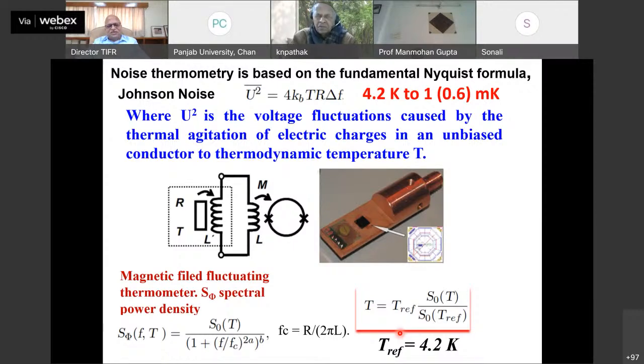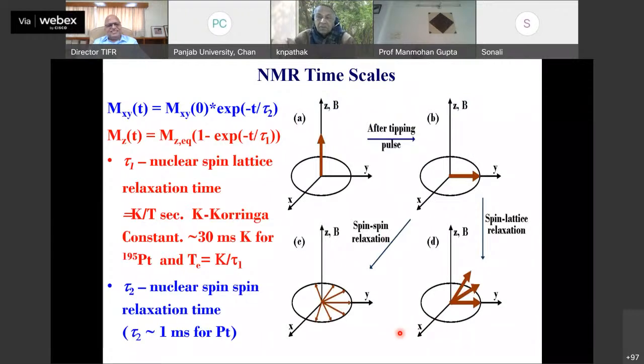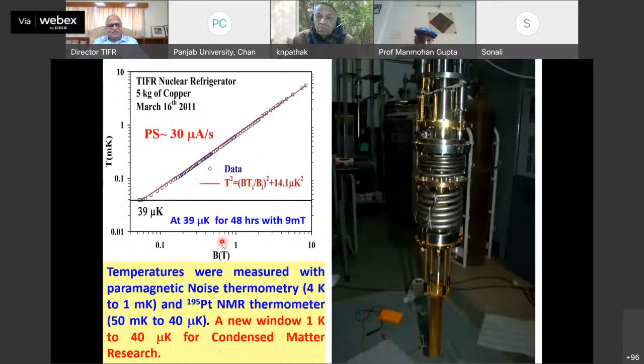Then use this noise sensor to calibrate the NMR thermometer. So what you do, the magnetization goes as M_0 (1 - e^(-t/tau_1)), where tau 2 is the spin relaxation time, and tau 1 is the spin lattice relaxation time. So by measuring the magnetization at different temperatures and taking the ratio, you can also measure the temperature, which is used from, let's say, 10 millikelvin to about 1 microkelvin. If you don't know right now, you can ask me later. I can explain exactly how we measure this. So I'm going to skip that.